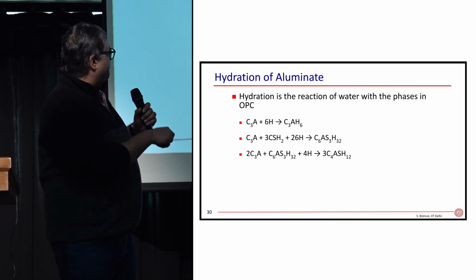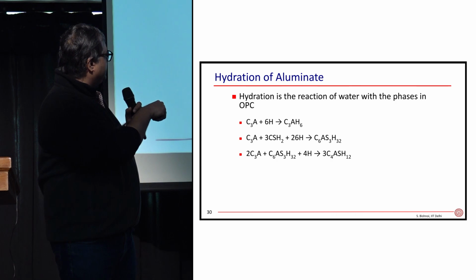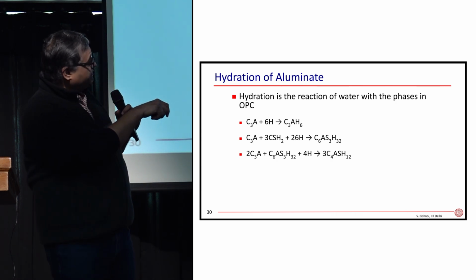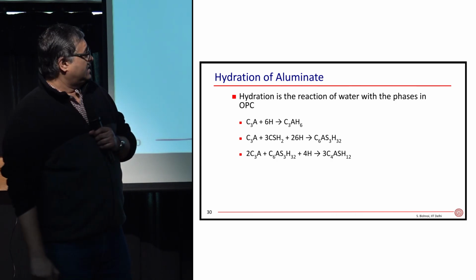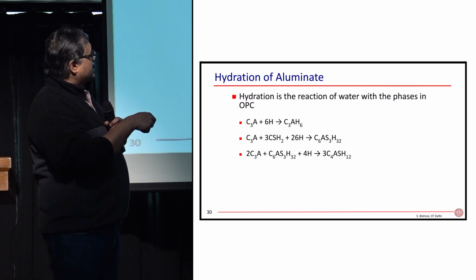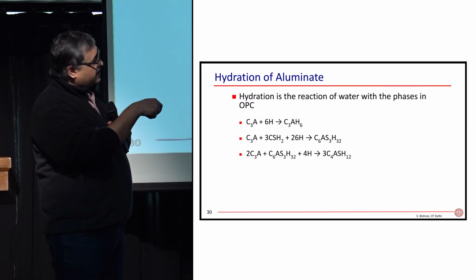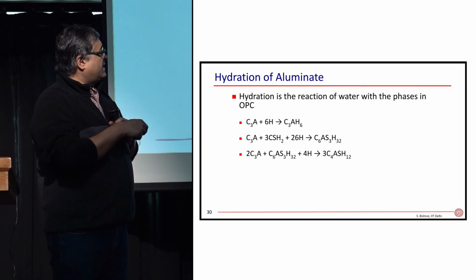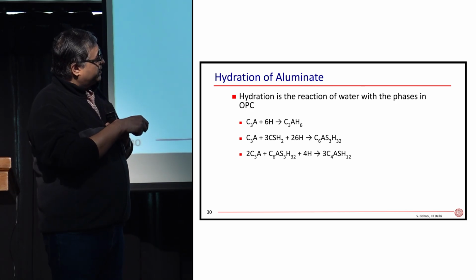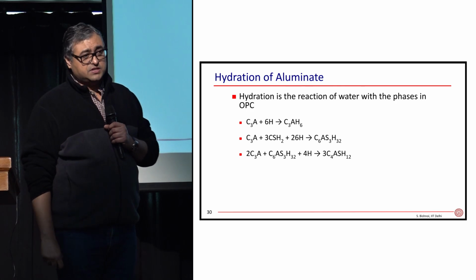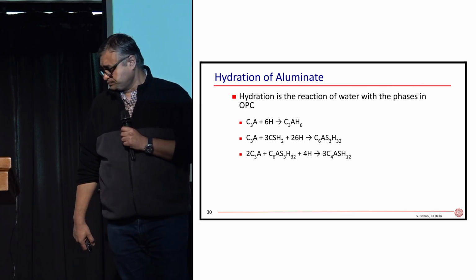When the gypsum runs out, the C3A will react with the ettringite to produce monosulfate, or monosulfoaluminate - this is calcium sulfoaluminate. Ettringite contains three sulfates, while this one contains a single sulfate - this is calcium monosulfoaluminate.